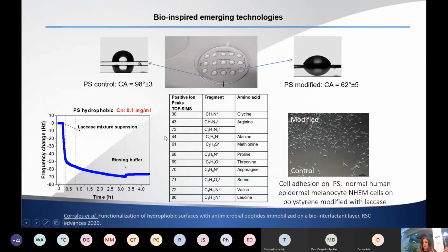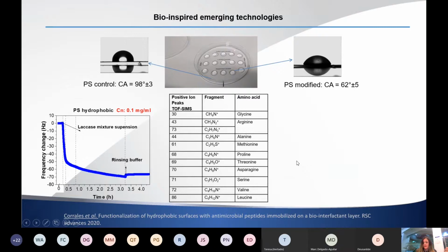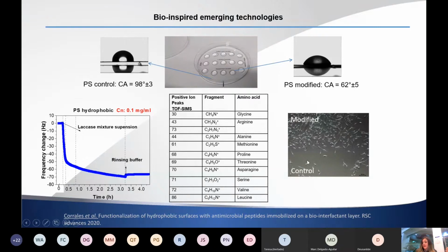So here I will show you an image where we see the control part, where we tested the addition of melanocytes, and we saw that on pristine polystyrene almost no cells adhere. And when we made this treatment with laccase, the cells preferentially adhere and really well. And also, we can treat the surface of a polymer quickly, and we also expose many functional groups that can help to attach another molecule.